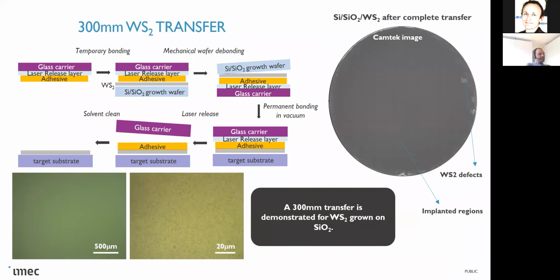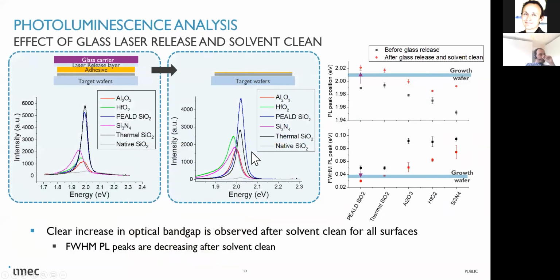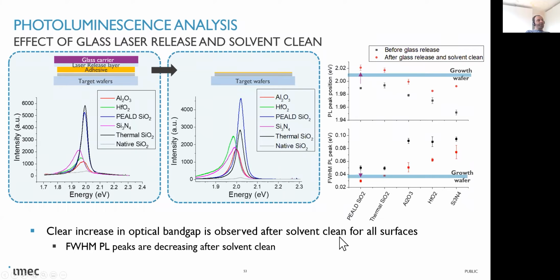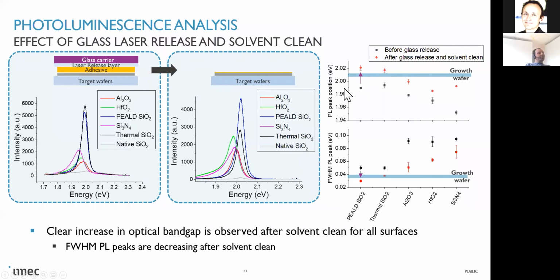Basically, this yields a kind of transfer where, in this microscope image, the quality of the layer looks very similar to the quality on the directly grown wafer. What you also can see is that the photoluminescence peak position gives an idea about the strain, and there is indeed some strain buildup during the whole transfer. But the good thing is that it's mitigated in that adhesive layer, and when you remove the adhesive layer, you can release and come back to strain levels that are almost at the same level as before you start. So this is kind of promising.